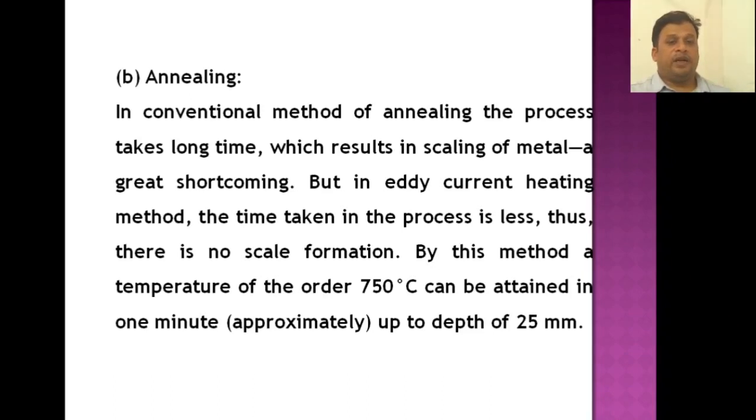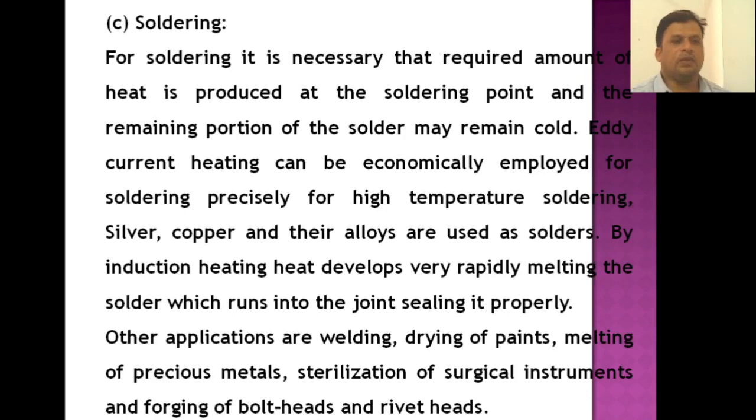But in the eddy current heating method, the time taken in the process is less, thus there is no scale formation. By this method, a temperature of the order of 750 degrees centigrade can be obtained in 1 minute up to a depth of 25 mm. This is annealing. In the annealing process, high frequency eddy current heating is more favorable than the conventional methods.